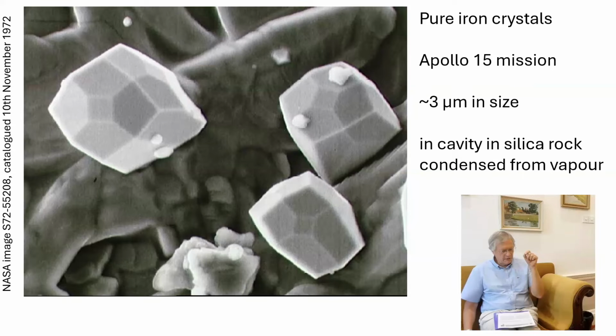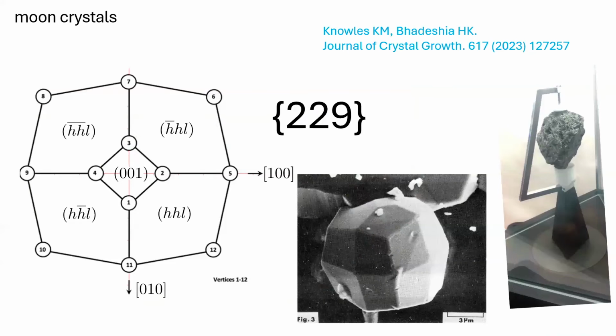So Kevin Knowles worked on this for roughly 3 months, and we solved these 5-fold faces. And they are weird, {229}, not 100 or a simple face. So why should a self-respecting crystal have weird faces? And he solved the faces to be {229} intersecting with 001, which gives us the 5 sides. And then I used the image in my book, and we also published a paper on this. And when I talked about this to other people, I said, this will never be cited, because this doesn't change the world as we know it at all. It's very interesting, but it doesn't change the world as we know it.